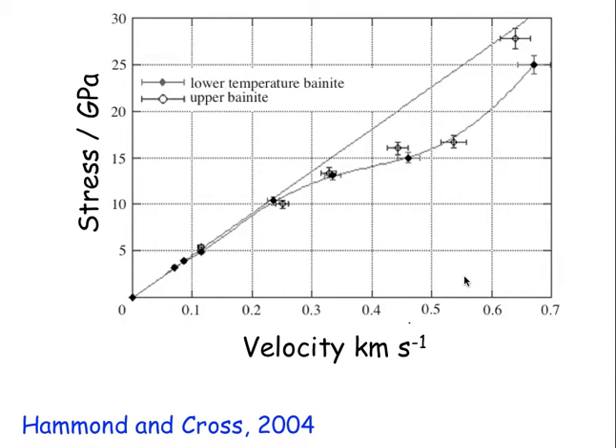Some examples. This experiment done in the Cavendish measures strength as a function of very high velocity impacts. If you deviate from the straight line, that means you've got plasticity. At very high strain rates, you've got a strength of 10 gigapascals. Can you think of an application? Armor. This has been fired at many times - you've got to pass it around and feel the weight. It can take multiple shots.